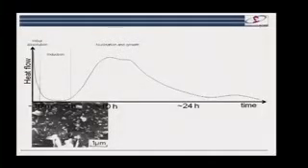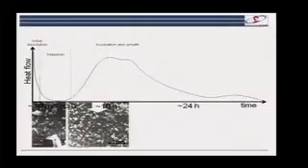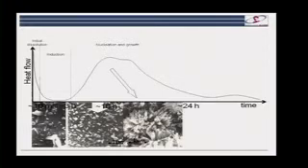So now let's look through this curve at what's happening microstructurally. If we look after about an hour or so, this is the surface of my alite grain. This is a big alite grain here. This is 1 micron. And on the surface of my alite grain, I've got a few little rods of ettringite. I showed you before that this ettringite formed very early on. And maybe a tiny bit of CSH is also starting to form. I get to this point here, the end of the induction period, about 3 hours, and I'm starting to form my CSH, like I showed you before.